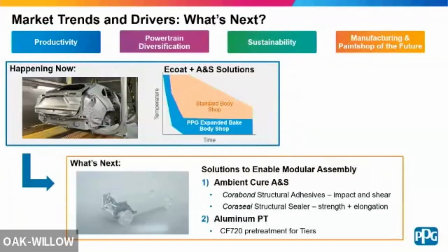So OEMs, and I'll speak from the Ecoat side, and then I'll let Lindy handle A&S. We already have a lot of OEMs that are already pushing to 140, right? And I'll be honest, from an Ecoat perspective, it's a lot easier for a line to handle 100% aluminum than it is mixed metal. So we see the issue a lot more on tiers, where a tier's line used to be 100% carbon. And then all of a sudden it went to 80, then 60, and now you're down to 40 because they just keep packing more aluminum.